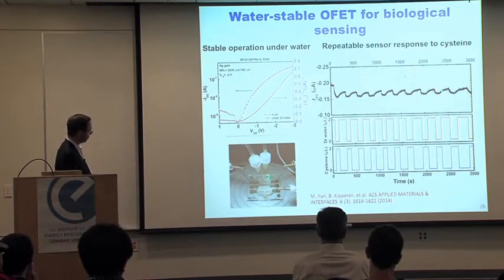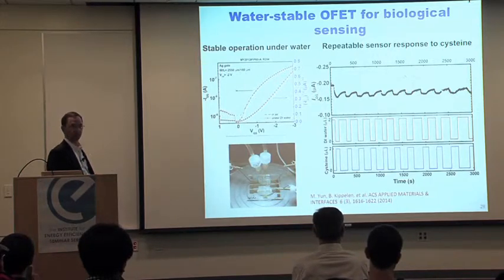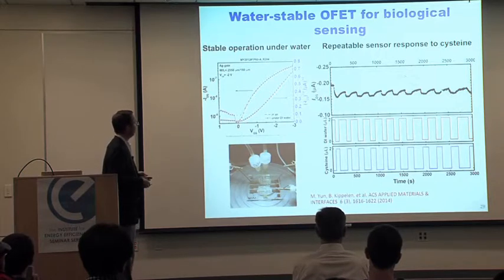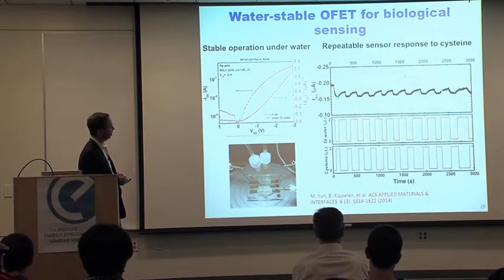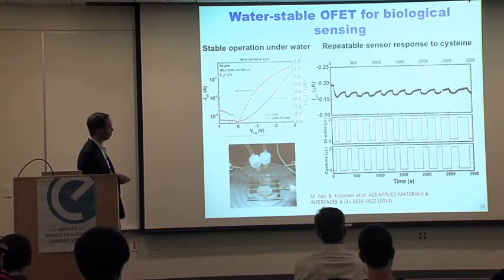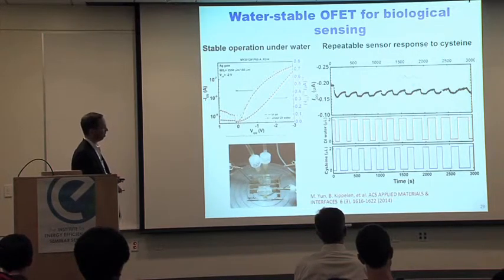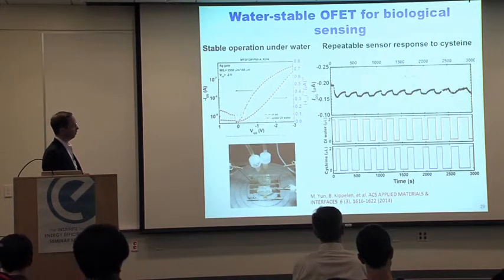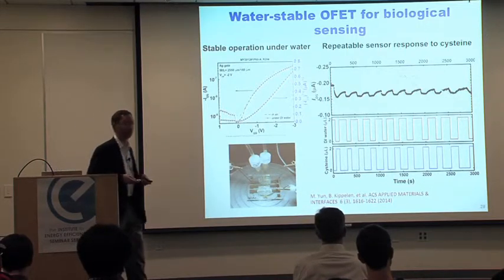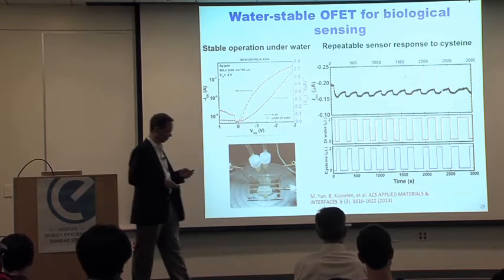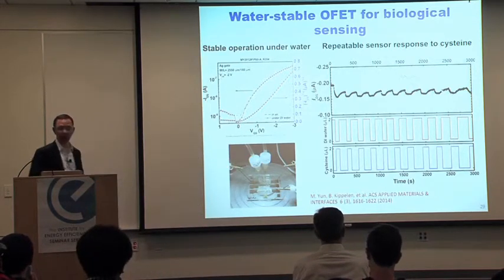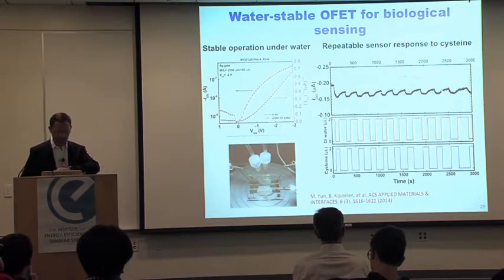Now remember, these devices are so stable in water, we started to use them as sensors. And so one of my postdocs started making microchannel devices out of PDMS and started to run a continuous water flow on top of these transistors. There is no degradation under continuous water flow, and we wanted to test these devices as sensors, so we introduced cysteine in the water, and then we just ran regular water, included cysteine, ran regular water, and so on. You can see over time periods, which are hours, that it is a perfectly reversible, non-destructive sensing of analytes using these transistors. So you can do sensing, but it's really non-destructive sensing, which is really important.